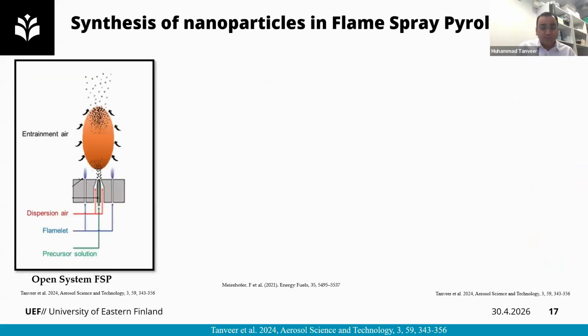So how does flame spray pyrolysis actually work? We have two options: we can use an open system or a closed system. This is an open system for flame spray pyrolysis. In this system, the precursor is injected into the reactor with the help of a peristaltic pump, and then a dispersion medium, a quite high pressure gas, converts the precursor solution into micro droplets. When these micro droplets are exposed to the flamelet, because the precursor is highly flammable, it ignites and undergoes reactions, because we have oxygen here from the entrainment air and also from the dispersion air.